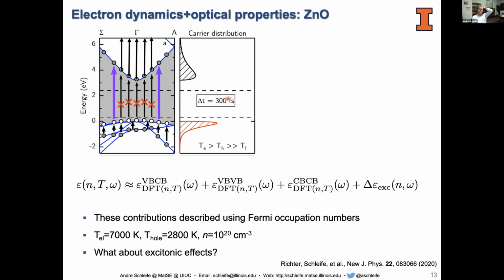Okay. What that looks like in the band structure is the following. These excited electrons occupy lowest conduction band states, of course, and you see the distribution here. And what that leads to is an effect called the Burstein-Moss shift. So meaning transitions from the valence states into those lowest states cannot happen anymore because the final state is occupied. So that needs to be taken into account. The second effect is a band gap reduction, which also occurs due to the occupation of these conduction band states.